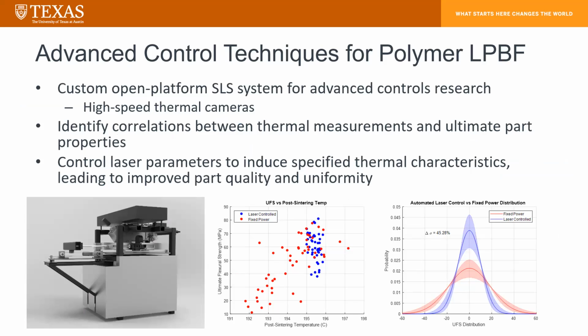During a build, we'll use our high-speed thermal camera to monitor the build conditions. And then we'll later identify correlations between what we can measure with our camera and our final part properties. So in the study in the middle, we're looking at the temperature that we measure with our camera and comparing that on the y-axis with the ultimate flexural strength of some parts that we're building. You see that there's a pretty big range here in the temperatures that we achieve, and that results in a pretty big range in the strength of these parts.